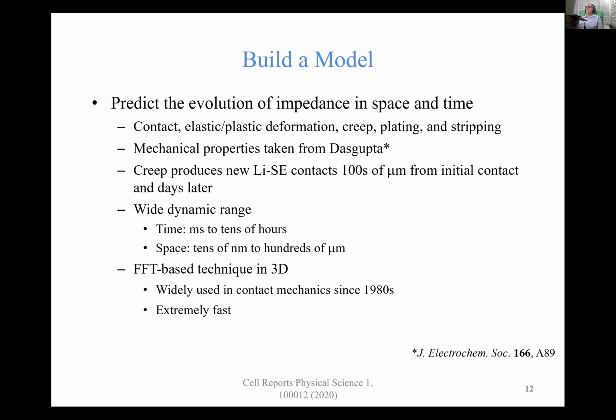So what we decided to do is to build a model that would predict the evolution of impedance. And of course, impedance is going to be related to the contact situation you have. And we're going to look at evolution in space and time. And the model is going to have information about contact, plastic deformation. We're assuming perfectly elastic, perfectly plastic. And it'll also cover creep, plating and stripping. The mechanical properties are going to be taken from Dasgupta, University of Michigan, with one exception that I'll mention in a minute. And it's also going to, as I mentioned, consider creep.